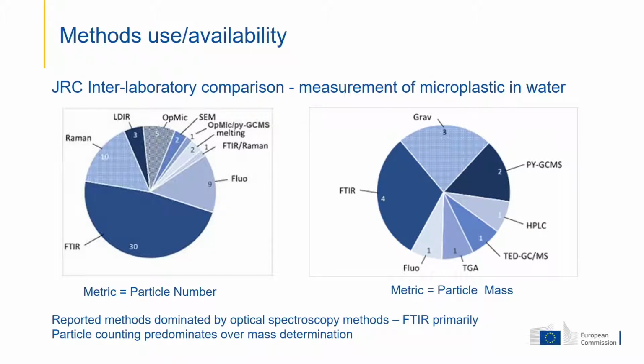I won't present any more data about this other than to show the distribution of the methods reported. As we can see, the use of FTIR microscopy is by far the most abundant, followed by Raman and fluorescence microscopy for particle number. It was noted that relatively few techniques were used for mass determination, and in particular pyrolysis GCMS, which is the most commonly reported method in literature, only had two examples actually reported.